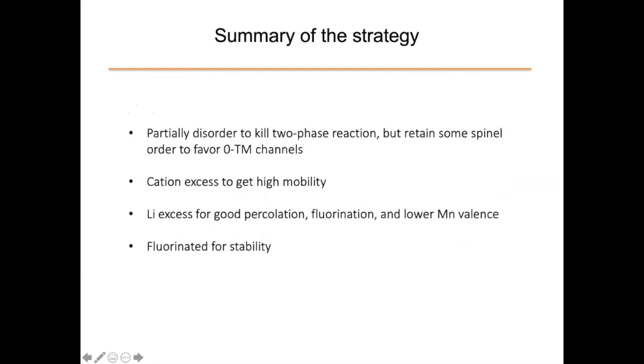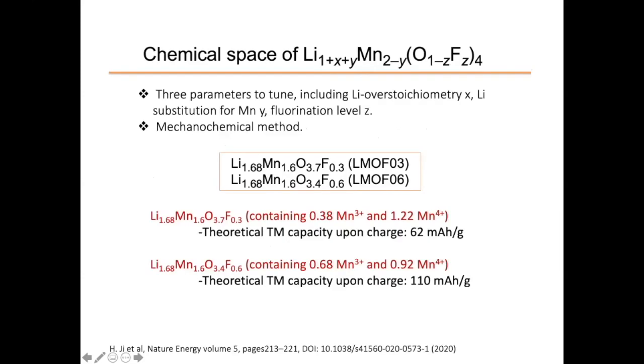Okay, so here's the strategy. We want to disorder partially to kill the two-phase reaction. We don't want to fully disorder it, because then we're back at rock salt. We want to get cation excess, so more than 3 cations per 4 anions, to get high mobility. We want to get lithium excess for good percolation, and we want to get fluorination for stability.